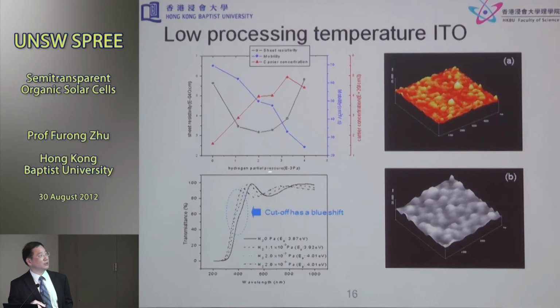The other thing we found that is very interesting is this transmission spectrum, measured for a set of ITO films prepared with different concentrations of hydrogen gas in the gas mixture during the sputtering process. And there's a clear so-called blue shift of the cutoff in the short wavelength range.